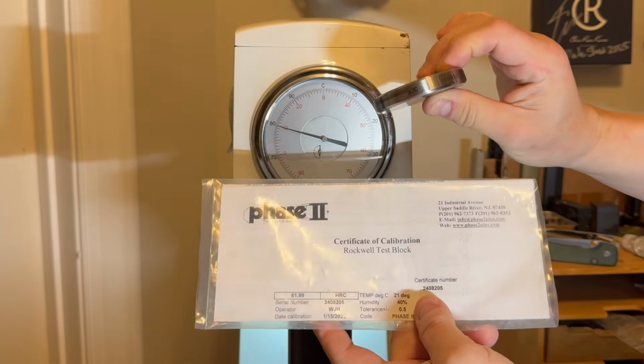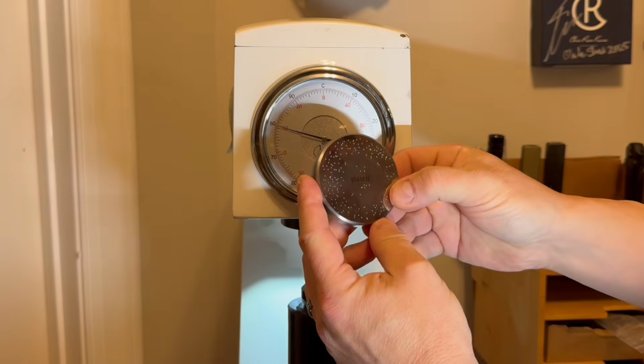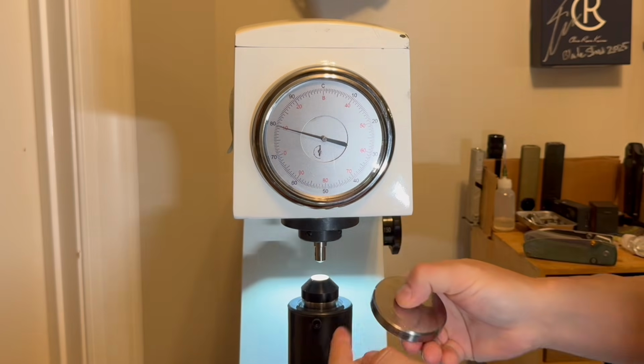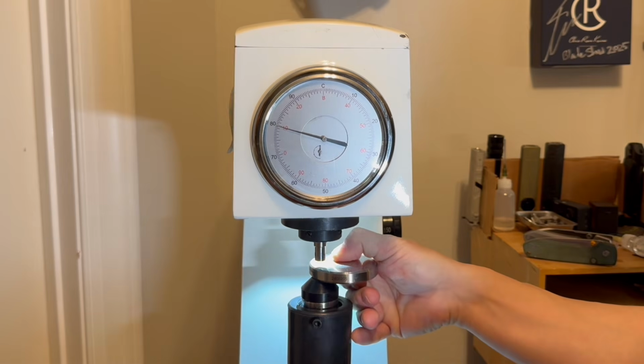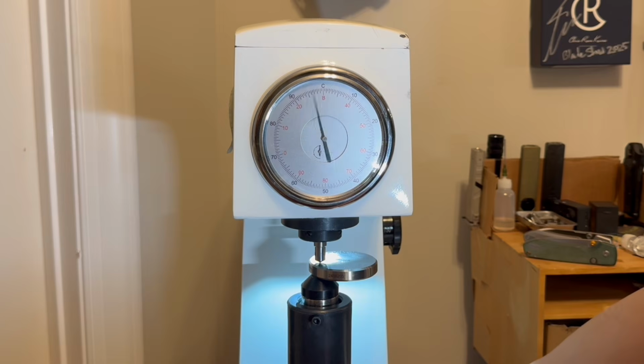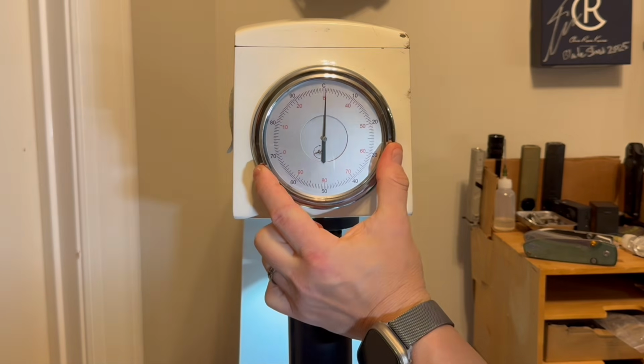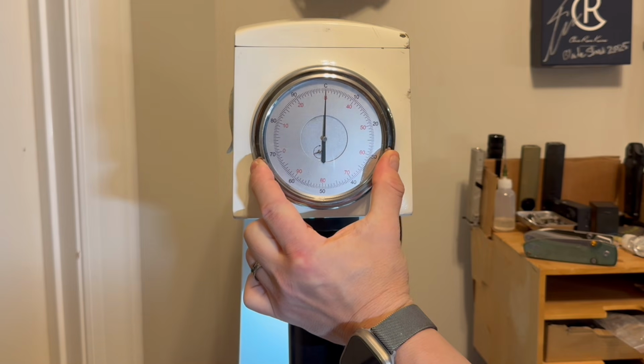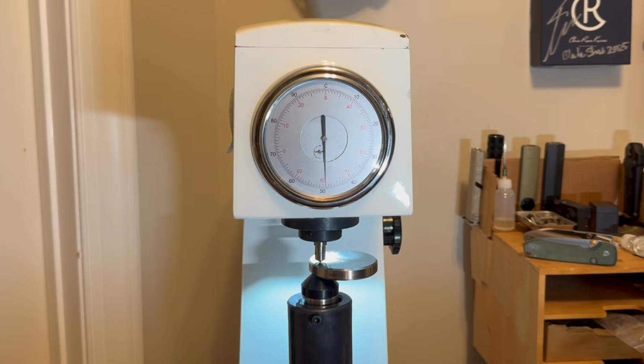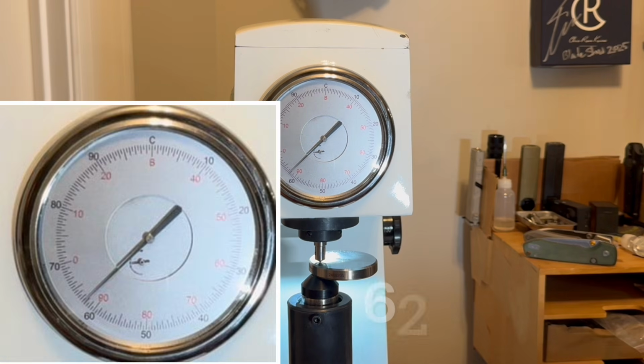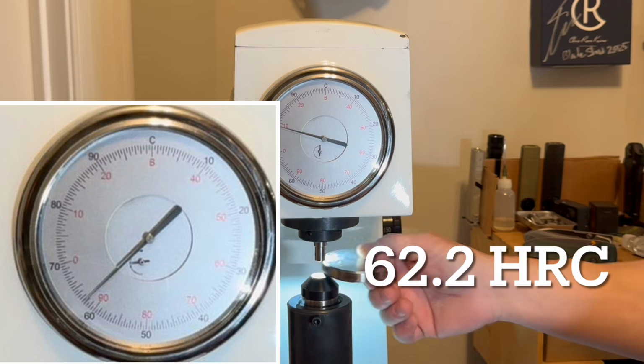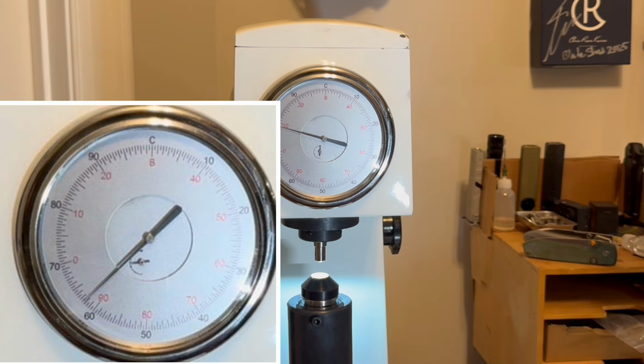I start all my hardness tests with verification of the calibration of my Rockwell tester. And for that, I'm using this serialized, independently certified calibration block. It's rated to be at exactly 62 HRC. My device always runs just a hair higher, so I should be getting somewhere between 62.1 and 62.2 HRC. And as predicted, 62.2 HRC.